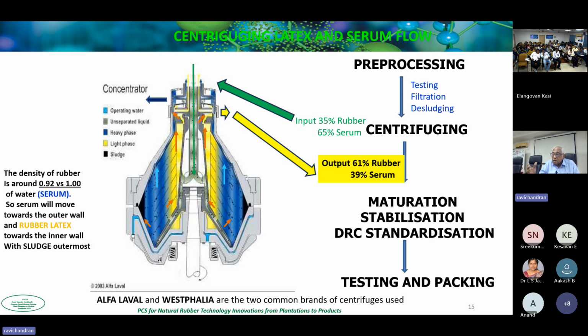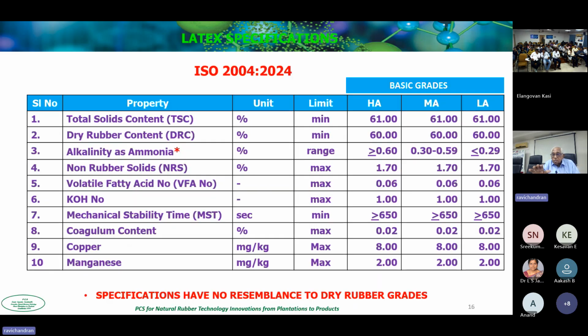So the latex stability, just after centrifuging, will be about 200 seconds. But after 3 weeks, the stability will go up to 700 to 800, naturally, because of the biogeneration of natural higher fatty acids. Then we test and pack it. And latex preserve can be kept for 2 to 3 years. So these are the main basic specifications for latex.